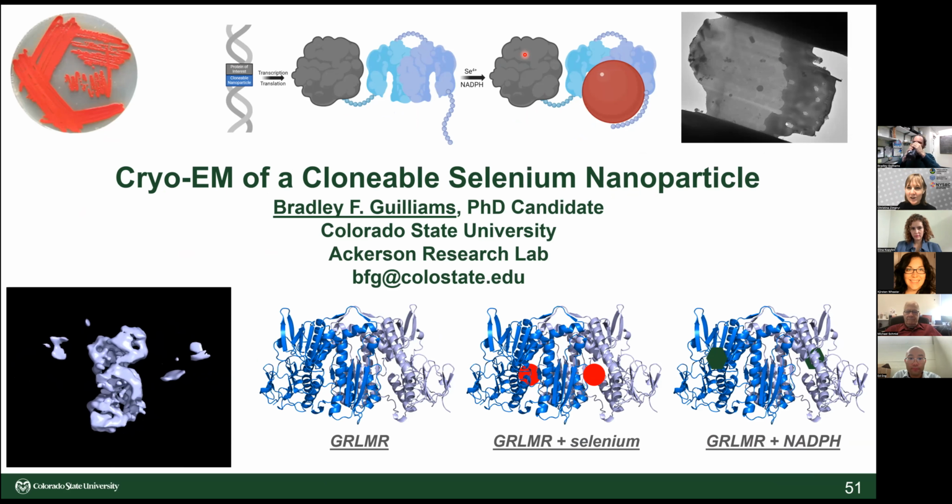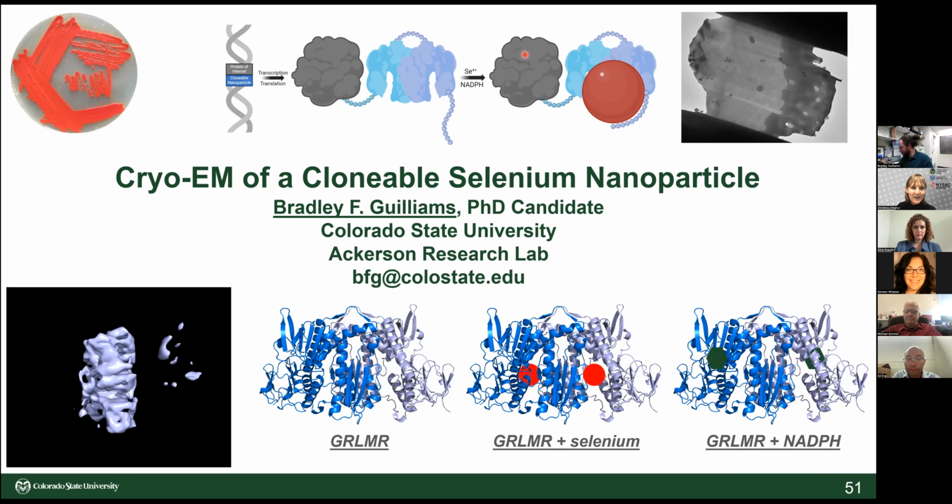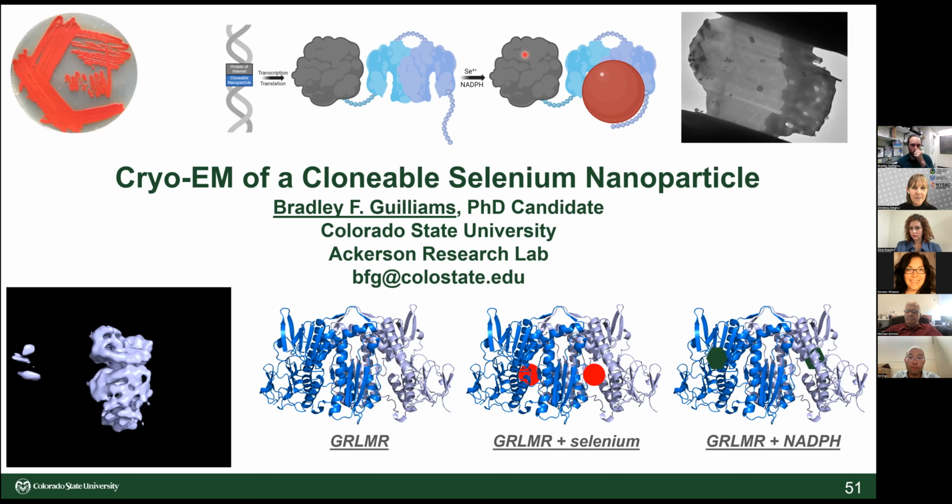I'll start with a question back more to the intro. What's the actual size of the selenium nanoparticle? Or if you don't know the actual size, maybe the relative size compared to... Yeah, so inside of cells, they're about 5 nanometers, plus or minus a nanometer. Outside of cells, and this is something we're trying to figure out, it makes larger particles when it's just in buffer.